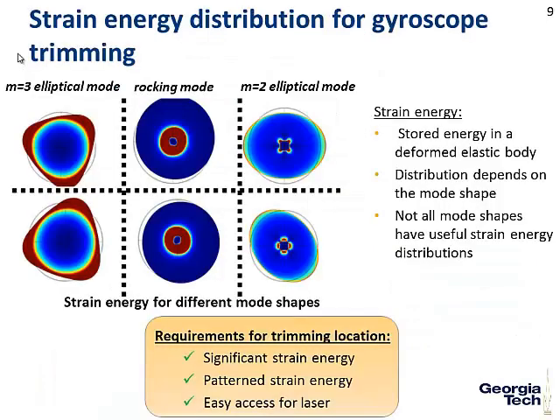Now, having strain energy is not everything for gyroscope trimming. You actually need a little bit more. If you look at the M=3 mode, you can see that there's strain energy all around, but it's a bit difficult because you need to add a trimming material on top of your device. So if you have a shell and need to put gold vertically, it's pretty difficult to do in fabrication. Also, you can see for the rocking mode, for example, the strain energy is at the bottom. So it's better access for a laser. The laser just comes from the top, whereas for M=3, you would need the laser to come at an angle to be able to touch that region.